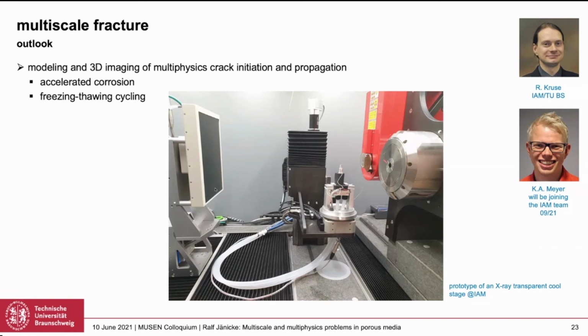So what we want to do in future is really to have multiphysics crack initiation and propagation. In view of concrete, interesting tasks are accelerated corrosion of reinforcements, and based on that, those cracks or damage zones around the reinforcements, if water is entering there, freezing-thawing cycles, because then this might lead to frost damage. And apart from the modeling side, we also would like to do 3D imaging of that.